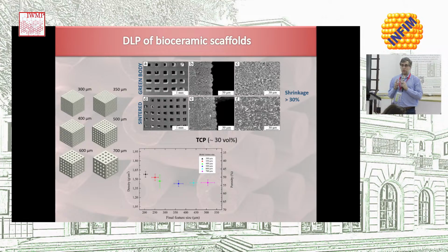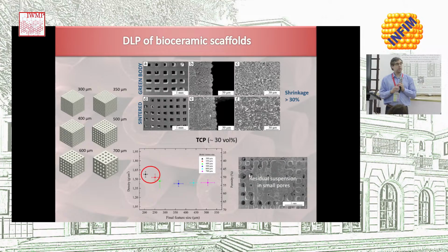And one of the things that we found out is that it's very complex to make very fine, very small pores, because when you do that, as you see at the bottom here, when you reduce the feature size of the pores, you start getting an increase in density, even though we designed this scaffold to have all of them the same density. And the reason for that is that you are not actually able to remove all the trapped resin from the scaffold. So at the center of those scaffolds, some residual resin remains, and during the sintering process, it becomes part of the scaffold. So it blocks the porosity, which is a problem. So you don't want that. Okay, so that's a limitation. In principle, DLP has higher resolution, so you could go to smaller pores, but in fact, you are limited in the size because of this problem with the trapped resin.